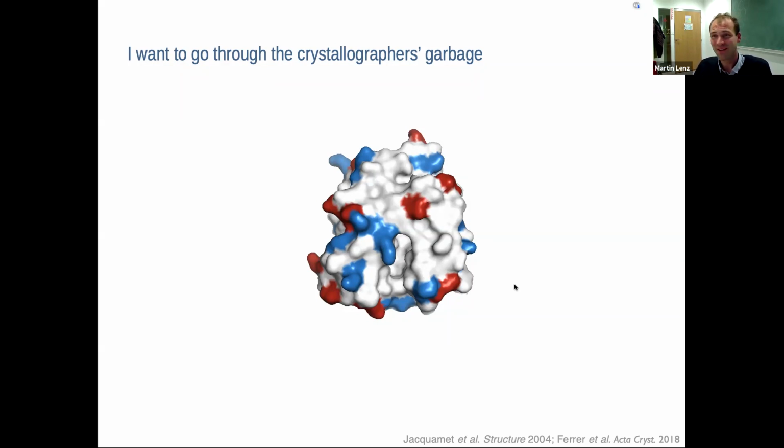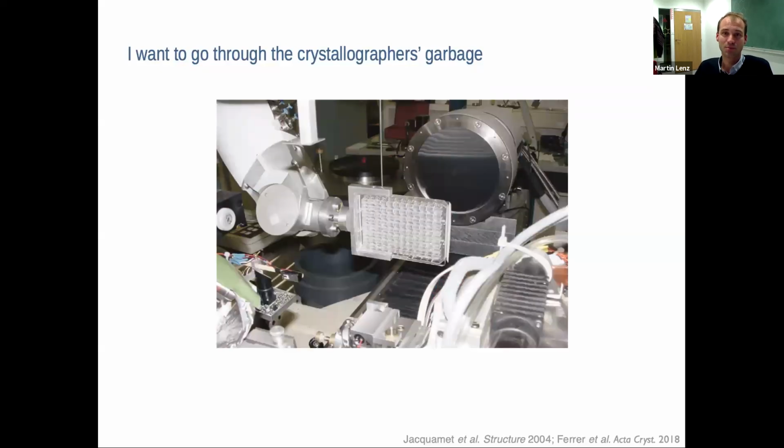But there's a lucky break, however, because there's a whole community that is doing those exact experiments, although for different reasons. And this community is protein crystallographers. What they essentially want to do is to produce protein crystals in order to resolve their structure. And to do this, they take their favorite protein and they put it in those crystallography plates in many different types of physical chemical conditions. Again, soap, salt, depletant, and many other things. And they try to push them together, but not too hard, because if you aggregate them very violently, you're going to make something very amorphous and not nice and crystalline. So they try to put themselves in the same realm that we're interested in. And they're successful, rarely. Essentially, the success rate, if you have a plate like this, is that 1% of the conditions that you tried are going to be a crystal, or maybe even less.